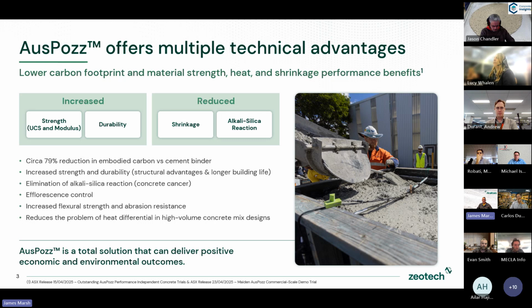And also, you'll see in the picture there was a trial we did recently at Holcim's biggest batching plant in Brisbane, where we were demonstrating that it can reduce the problem of heat differential in high volume concrete. We've got some very good results for that demonstration. In fact, we are going to be repeating that next week with an even higher replacement of cement, because the results for that particular trial were too good. It was just too strong at a 40% replacement. So we're now going to 50% replacement in that test week after next.